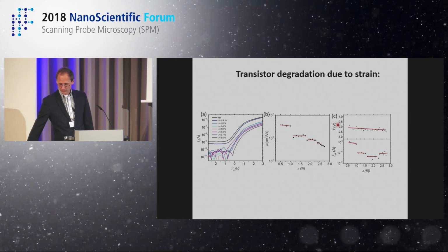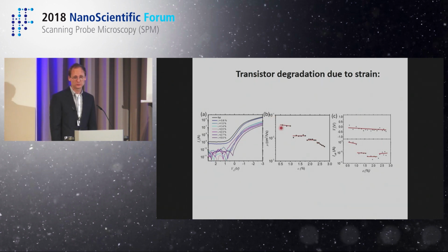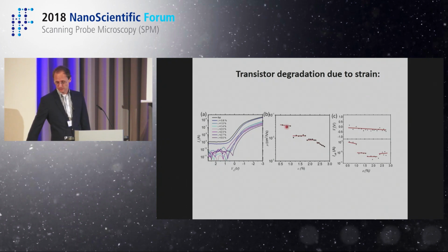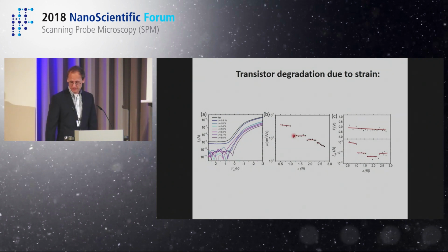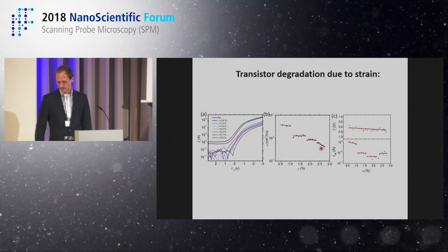And these are now the characteristics that show how such a transistor degrades. It can resist initially some bending up to roughly 1% of surface strain, and then it starts to degrade. You see that the degradation comes in abruptly, so you have almost an order of magnitude change in transport properties, but then it is again at a plateau, and importantly, it still maintains some transport qualities, and then it degrades further and further. This is an easy experiment to measure, but it's much more difficult to understand where the defect is, why it happens, and what I have to improve in order to have more stable electronics. And now the question comes, of course, how do I investigate this fracture mechanism in more detail?